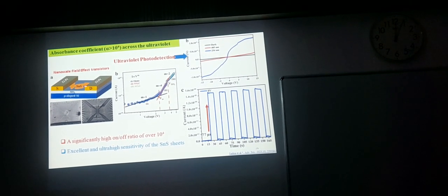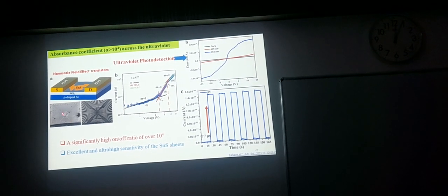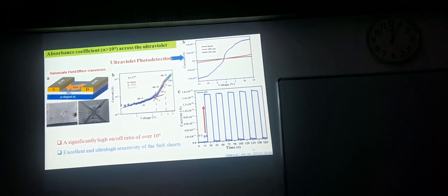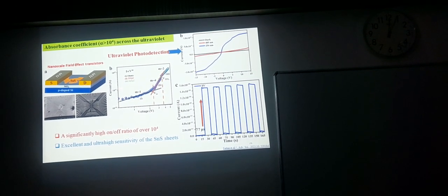Here you can see the single layer field effect transistor. And here you see the EBL lithographic devices, a scanning electron microscope image. We first studied the transport behavior of the single layer tin sulfide. You can see we have different regions with different transport properties: the ohmic region, then trap-filled limited space charge conduction, and the space charge limited conduction region in the system.